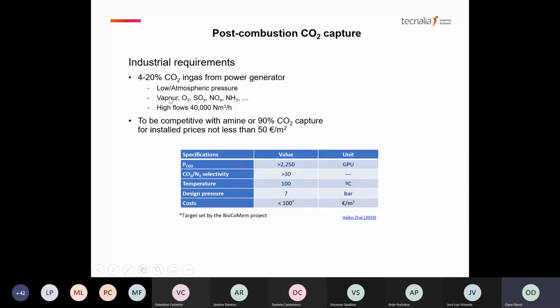But I will just briefly say that we have an inlet gas that contains up to 20% of carbon dioxide. And what is challenging is that it's coming at low atmospheric pressure and that it has very high flow. So compressing such a high amount of stream is very expensive. Therefore, in order to be competitive with amine, we need membranes that are highly permeable, about 2,250 GPUs, that would have a carbon dioxide nitrogen selectivity higher than 30.